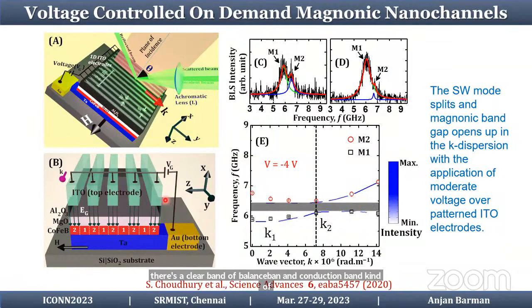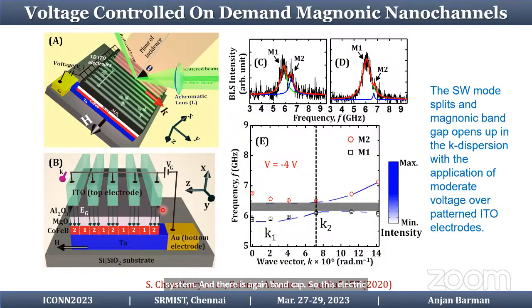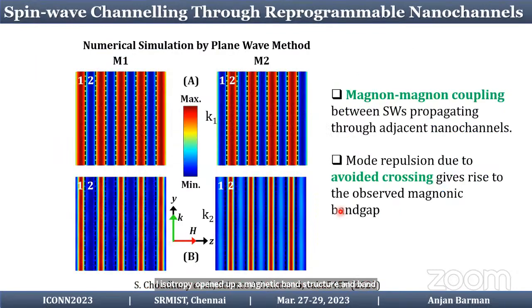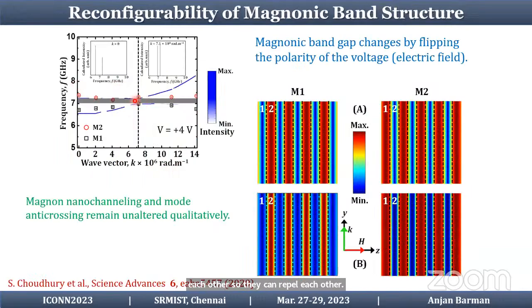So this electric field controlled switchable anisotropy opened up a magnonic band structure and band gap in the system, which is very unusual and very interesting. And we did this numerical simulation by the plane wave method, and we can see that mode 1 actually flows through region 1, whereas mode 2 flows through region 2, and they are adjacent to each other, so they can repel each other. So there is a mode anti-crossing in the system, which gives rise to this band gap.